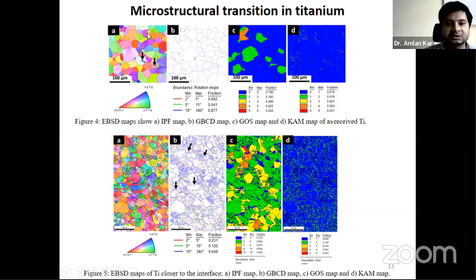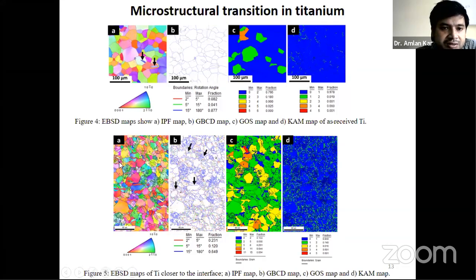Similar sort of thing to what we have seen in the interface, but the grain structure is very high here. The grain size is close to more than 50 microns. As we are moving close to the interface, we can see there is a huge fraction of twinning, and the microstructure also somehow refines compared to what we have seen in the base metal.